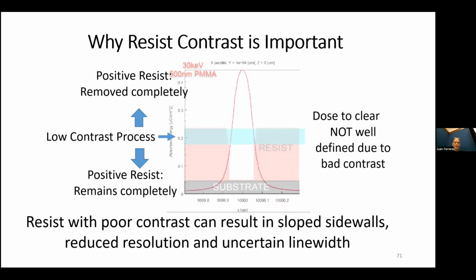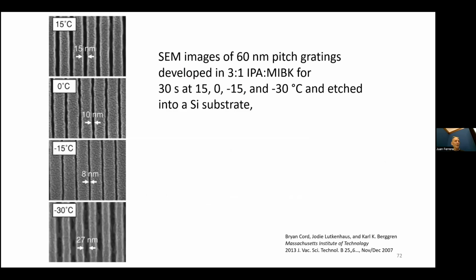One of the ways that it doesn't happen is something like this. If we have a low contrast process, that is, there's a range over which the dose will be enough to let some of the resist get developed away. And it's a terrible graphic. I was doing it yesterday, and anyway, hopefully I can make a better one. The idea here is within this range, we've got different amounts of dose, and then the resist itself gets developed away more or less. And now we've got sloping sidewalls. Sloping sidewalls are terrible when we try to transfer our process into a substrate.